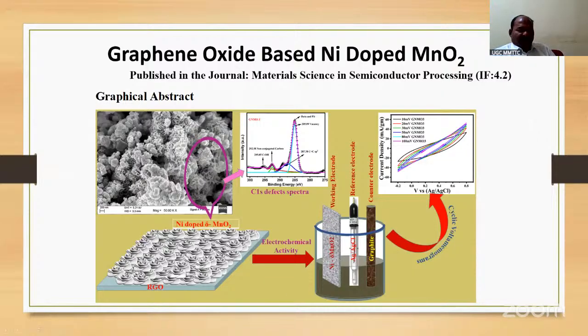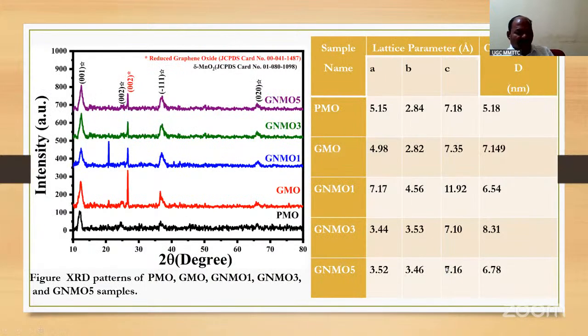Now graphene oxide based nickel doped MnO2. This is again interesting work. Here is the reference electrode, and this is the working electrode, and this is the counter electrode. This graphite is the counter and this is the working electrode, the nickel doped MnO2, and this is the reference electrode. Now you see the graphical abstract given here, and the X-ray diffraction patterns of the as-prepared samples with structural parameters outlined here.